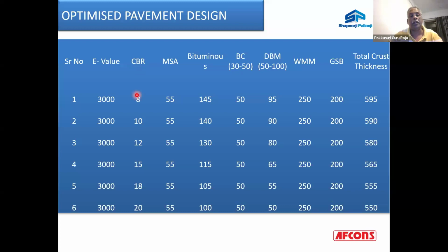And when you see the effective CBR is moving from 8, 10, 12, and 15, of course, if you look at the IIT PAVE, your effective CBR of subgrade should not be more than 15, because even if it is more than 15, it is not adding value to the mix design, because the deflection value or the K value is fixed at 100 MPa there.